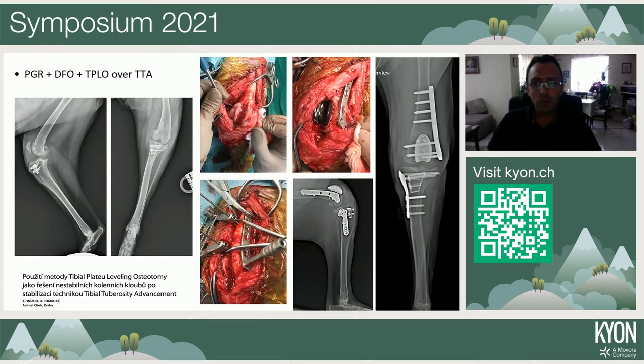In one much more complicated case, we had to treat a dog that was previously treated for a cranial cruciate ligament rupture. Unfortunately, the stifle was still unstable, in combination with a chronic medial patellar luxation. So we had to treat excessive distal femoral varus by performing a distal femoral osteotomy in combination with PGR, and then a TPLO over a TTA in order to stabilize the knee in the sagittal plane.